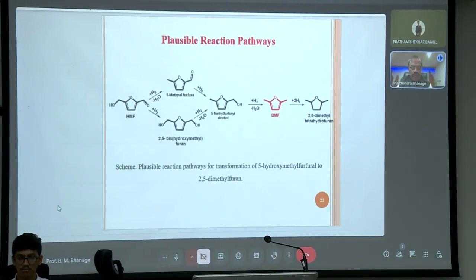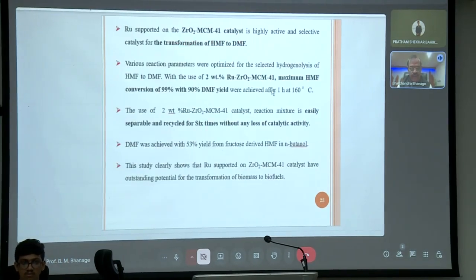So, when you want to do hydrogenation, you can see there are so many possibilities. HMF can be converted to 5-methylfurfural or 2,5-bis-hydroxymethylfuran. Further hydrogenation gives you 5-methylfurfuryl alcohol, which is converted to DMF. You may get over-hydrogenation to give 2,5-dimethyltetrahydrofuran. So, the challenge here is you have to develop a catalyst which will give you selectively DMF, and no other byproducts are found. And we worked in that direction.